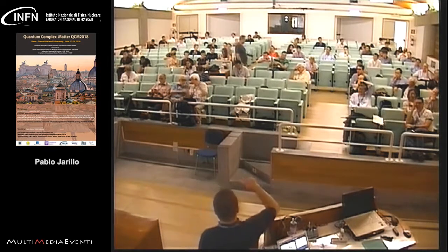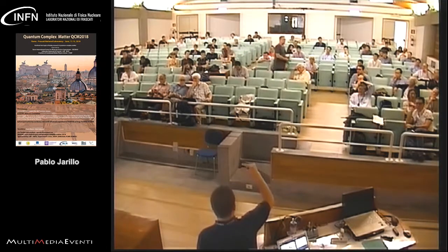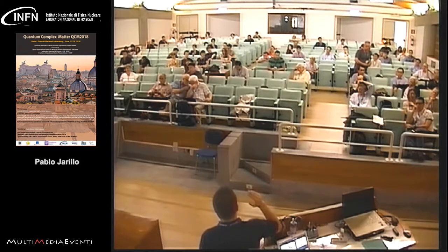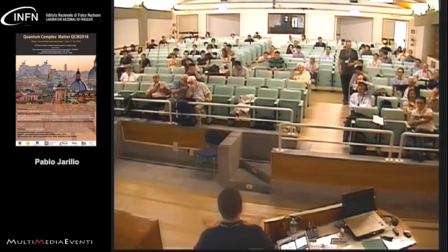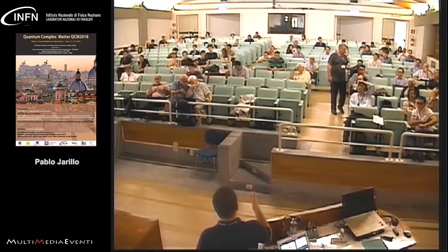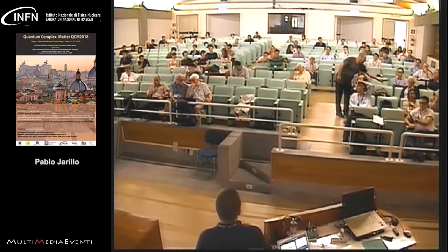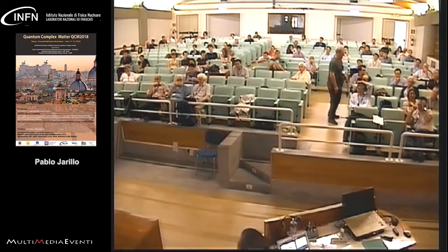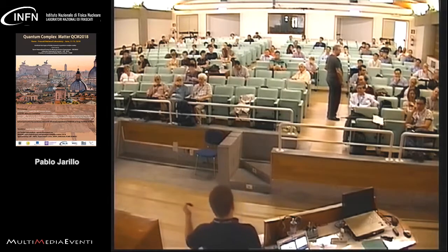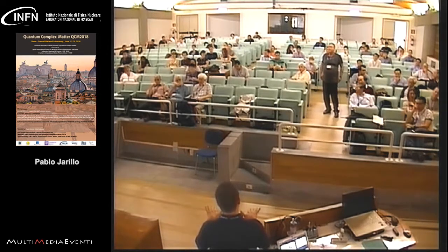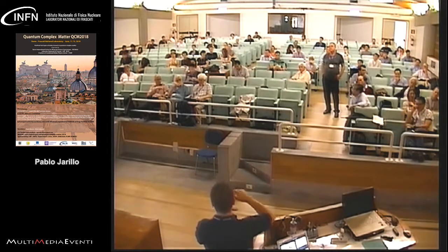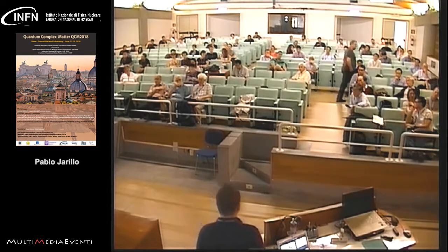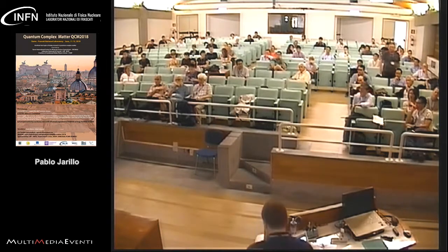Yeah. So for the full filling, the single particle gaps, in the experiment, we see them of order 30, 40 millivolts. Okay? The latest calculations, which include relaxation in the X, Y, and Z direction, predict gaps of similar magnitude. It comes from part of the relaxation, yes. Koshino has a paper in 2017 doing XY relaxation where already those gaps are of order 15 millivolts. And if you now include relaxation in this direction, people seem to see bigger gaps. Yes.